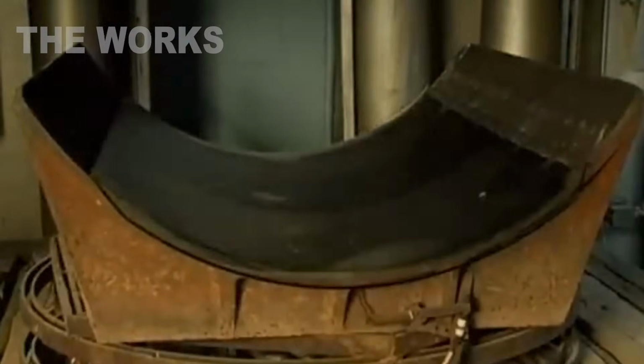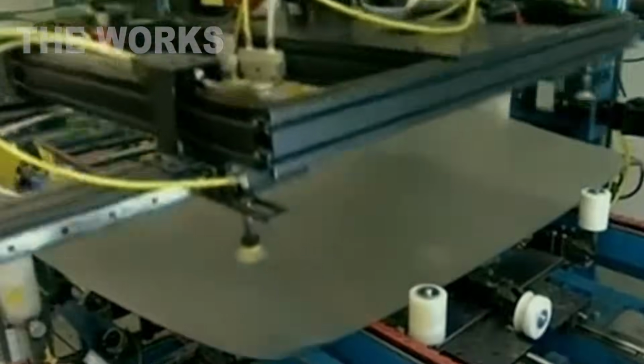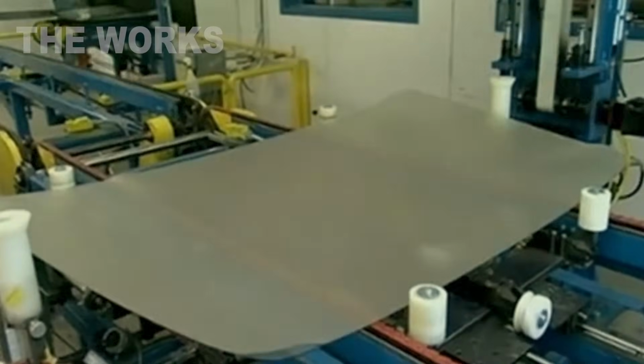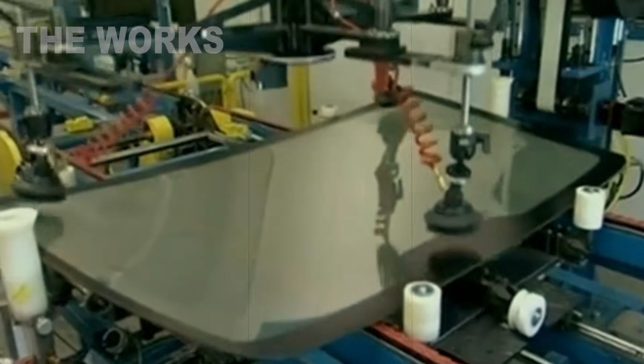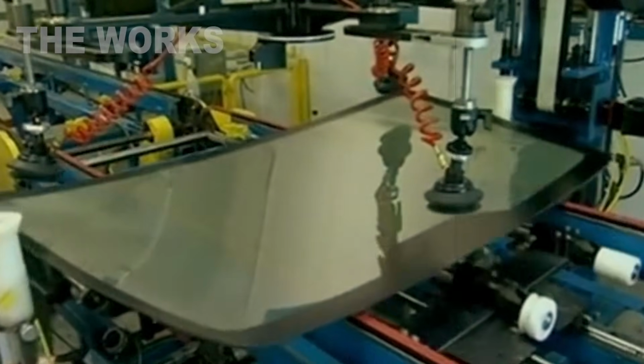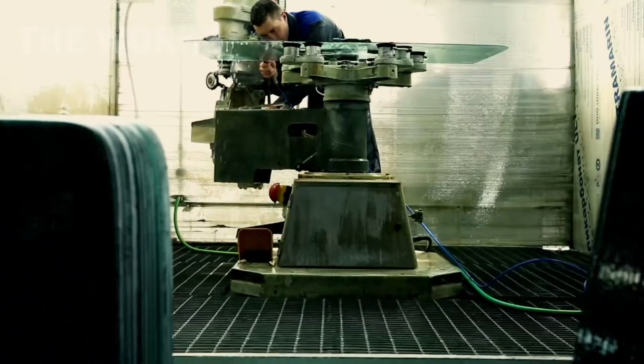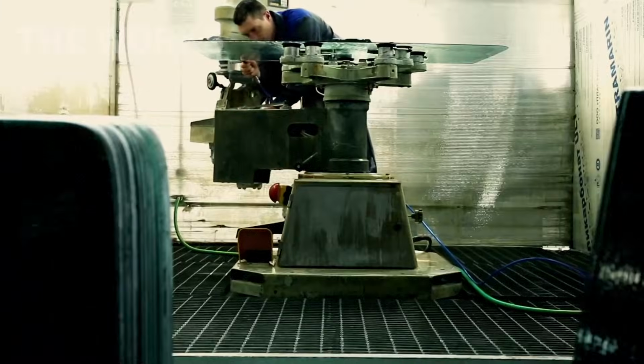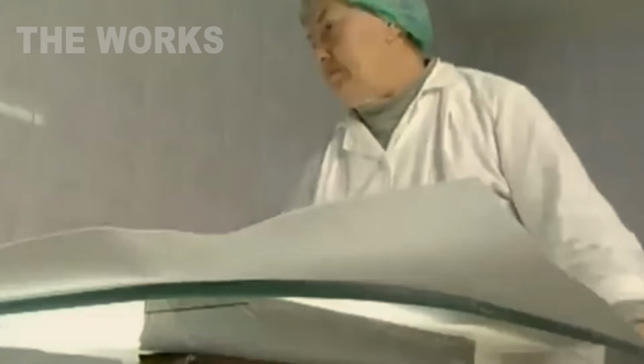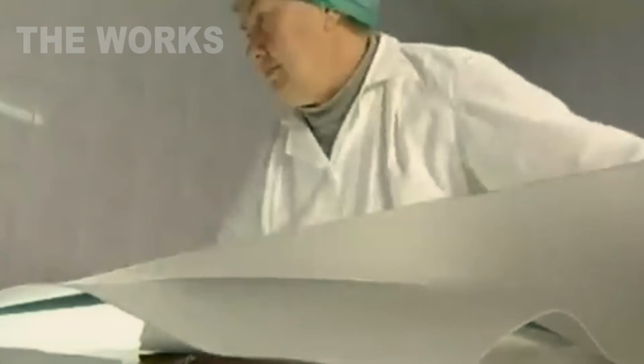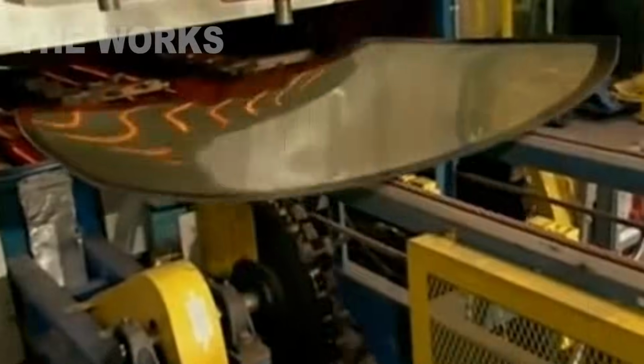Liquid glass flows out of the furnace and enters a bath of molten tin. Thanks to tin's high density, the glass mass spreads evenly across its surface. Under its own weight, the glass forms a perfectly flat and smooth surface. Gradually lowering the temperature, the glass hardens. By the time it exits the bath, it's ready for processing. The float method allows manufacturers to produce glass sheets with precise geometric parameters and high surface quality.